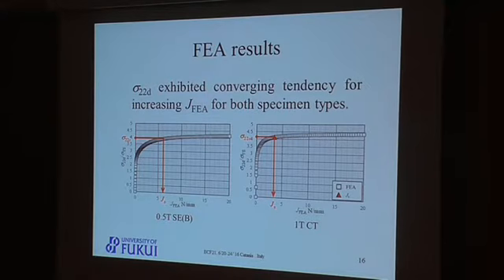Considering the fact that fracture always occurred after σ22d reached σ22c, we thought that the minimum J that could satisfy σ22d equal to σ22c, hereafter denoted as JS, would predict the lower bound fracture toughness for the specified specimen at the specific temperature.